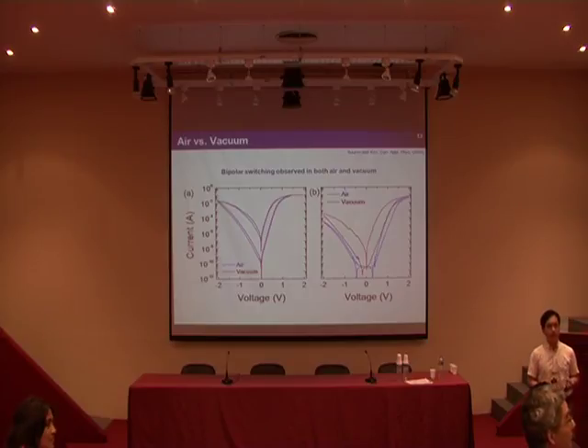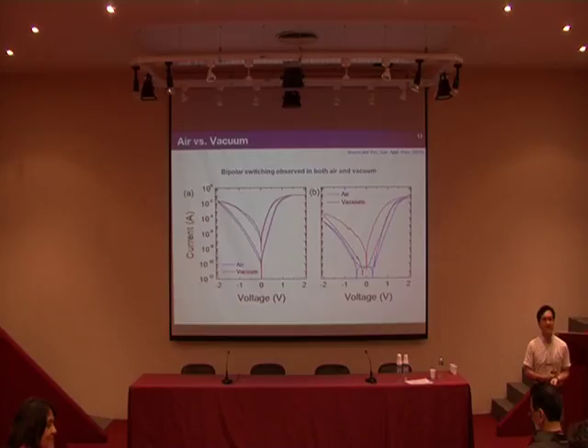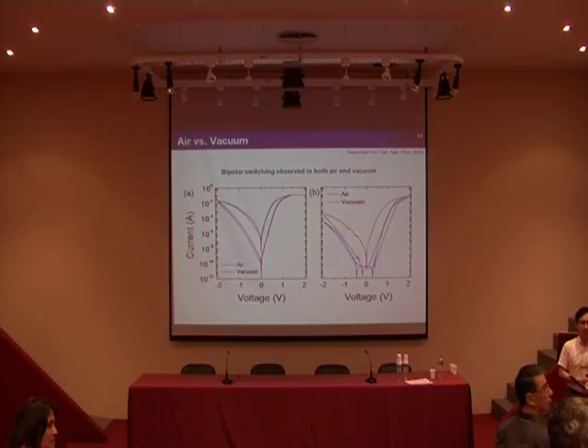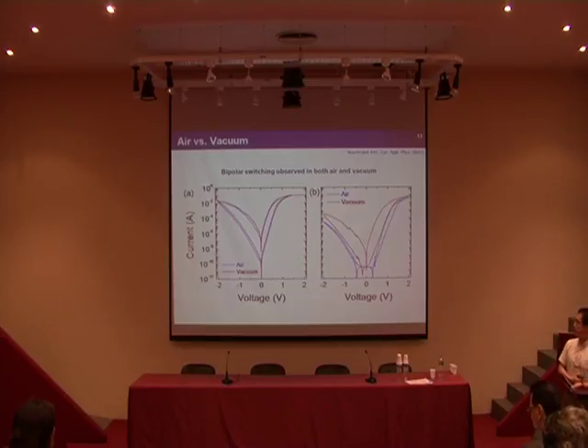I'm sorry, I disagree with that. I disagree with that, I'm sorry. The reason why you see that is because there's an offset current when you measure. When you take the log, that's what happens. So if you remove the offset current at zero bias, then that thing would disappear. Correct? Offset current at zero volts - when you do that measurement, then you see a little bit of current. At zero volts, there should be no current, unless there's a real current. That's all I wanted to say.